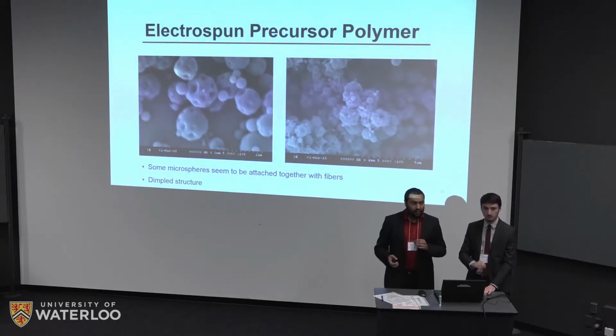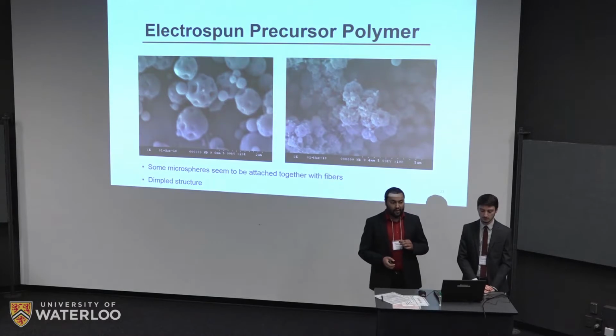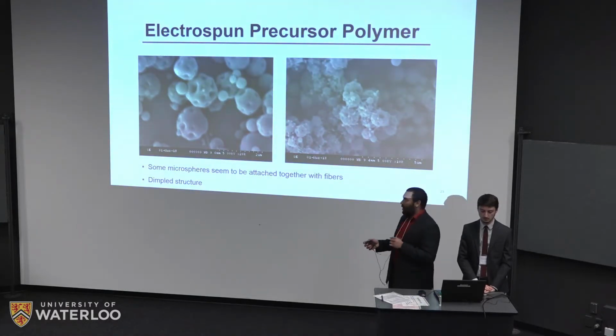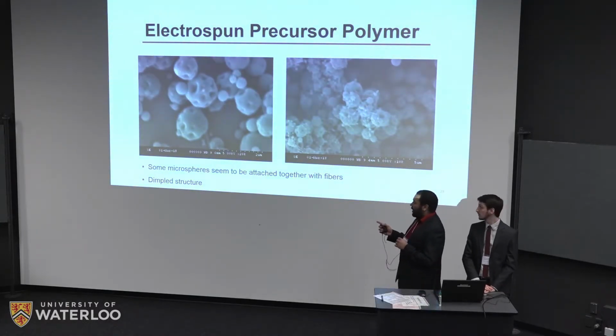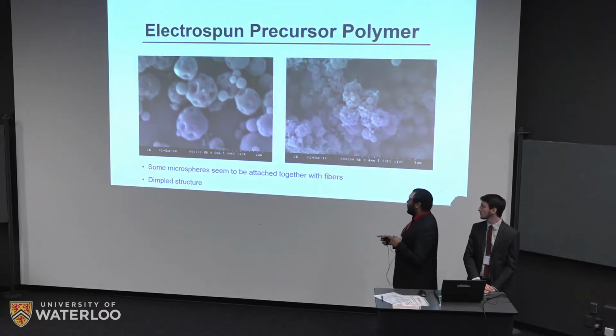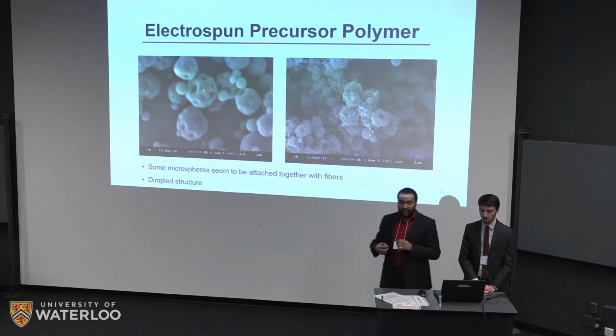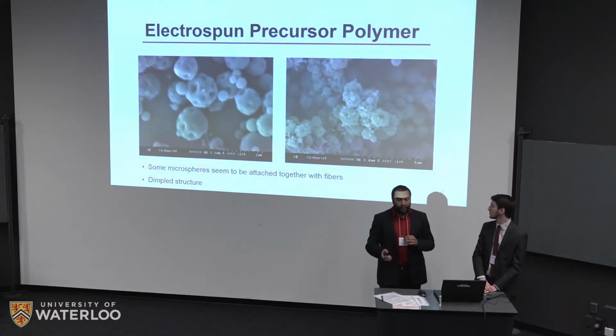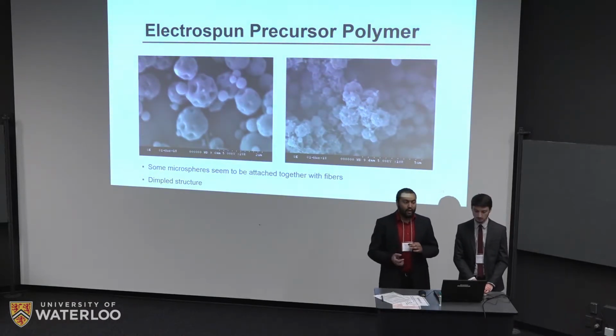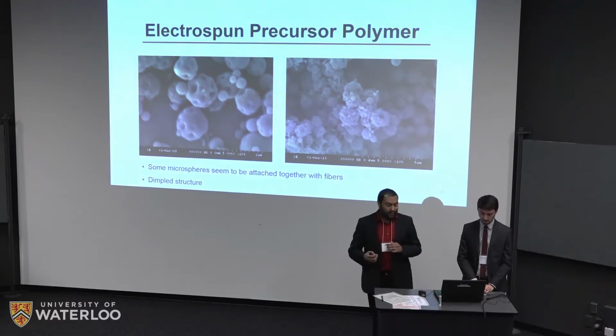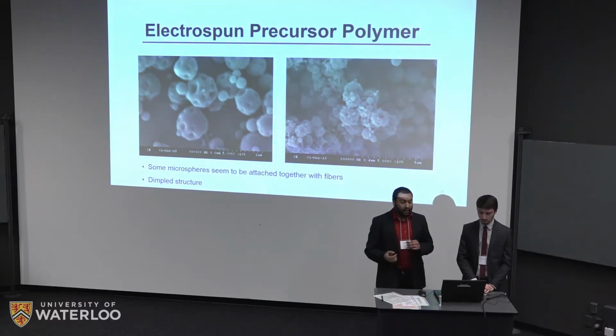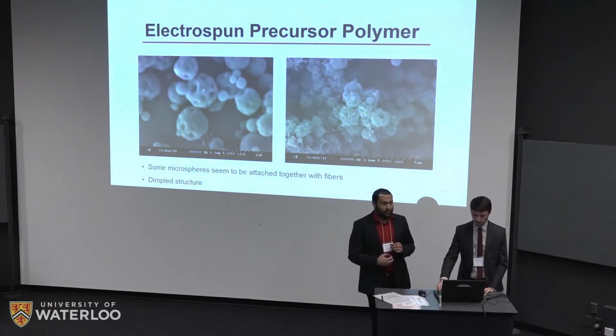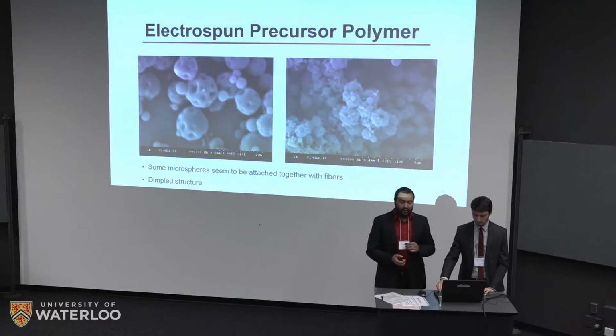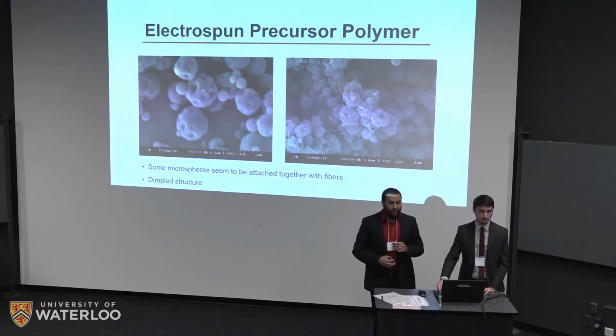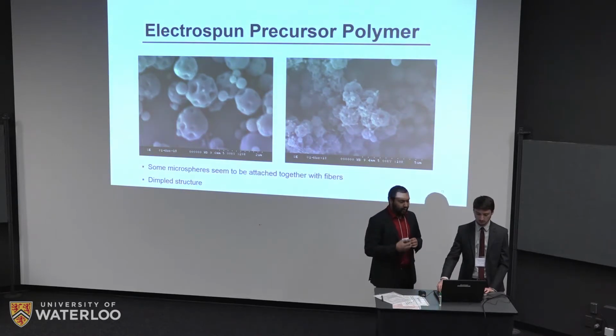These are some more zoomed in pictures of the same sample. We noticed we got a dimpled morphology for pretty much all of the microspheres that we looked at, and we also got some fibers connecting the spheres together. Overall, this wasn't the exact morphology that we were looking for, but we did end up getting good coverage and fairly good uniformity in terms of the size of the microspheres. And we know that we have successfully made our polymer, so we decided to move forward with the nanomaterials.